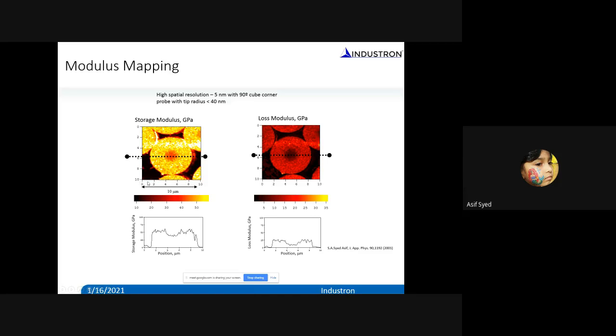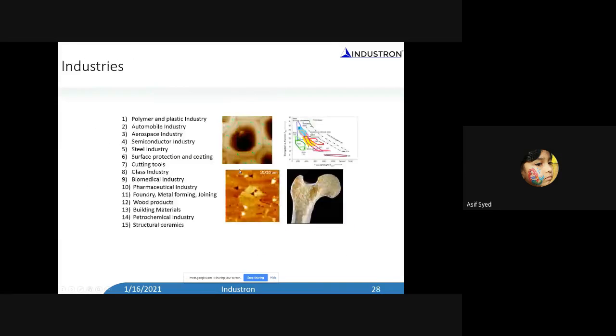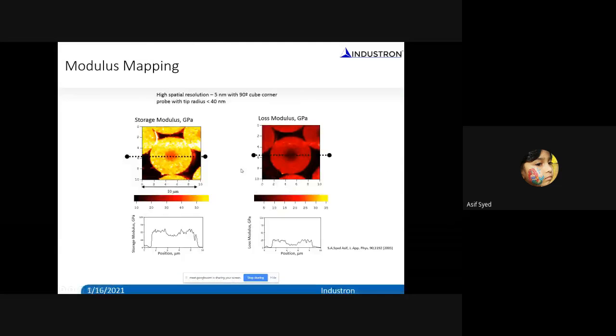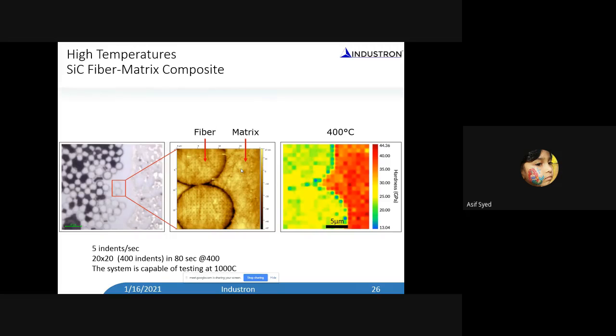So instead of measuring the modulus at one point and then neighboring points, in this case, it is basically 256 by 256 points, which means that if you want to do that many indents, it will probably take about 30 days, but we can do this imaging within like 5 to 10 minutes. So now you have a high throughput of data. You can go and image the property as an image, and that is very useful.